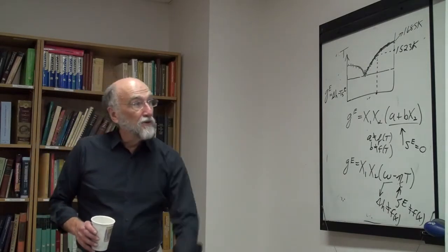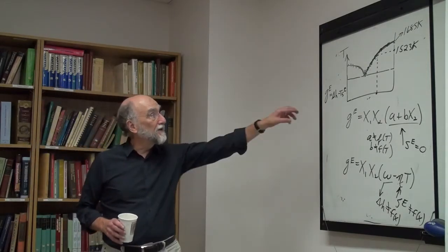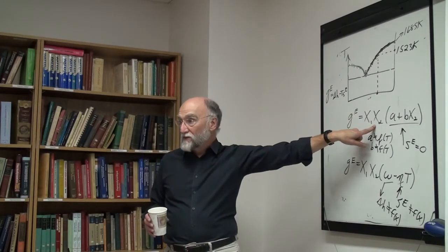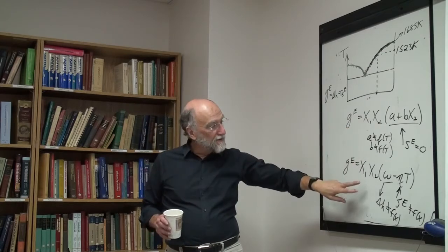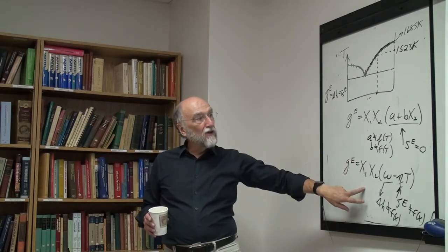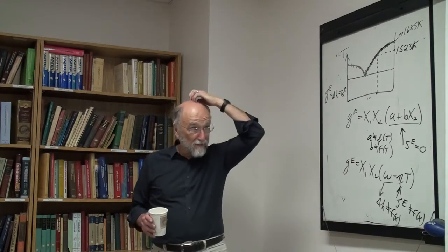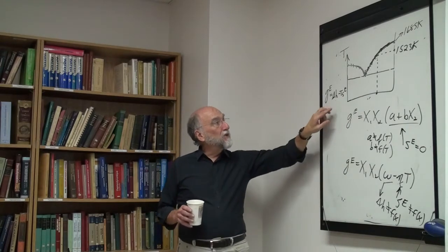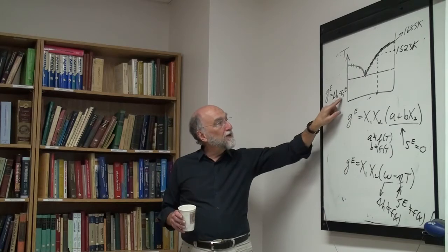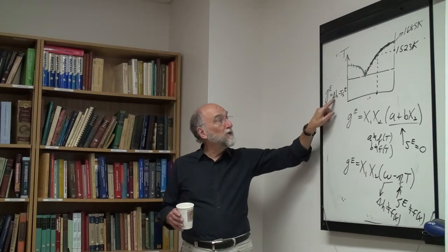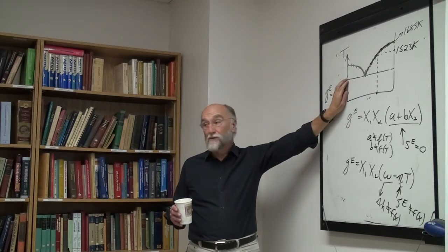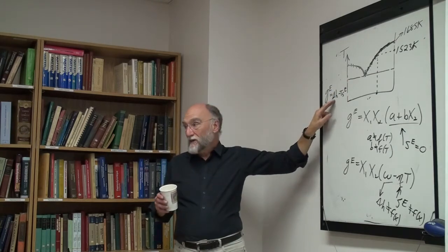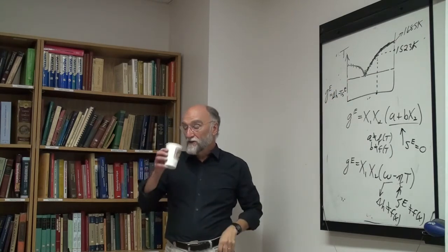In something like the gold silicon system, this is most likely true, because the thing is so close. When things are close to ideal, generally, we'll talk about this later too, if the system is close to ideal, then this term tends to be bigger than this term. In other words, if you're going to assume that one term or the other is zero, you'd better assume it's close to a random mixing, and the heat of mixing term is where the deviations tend to be.